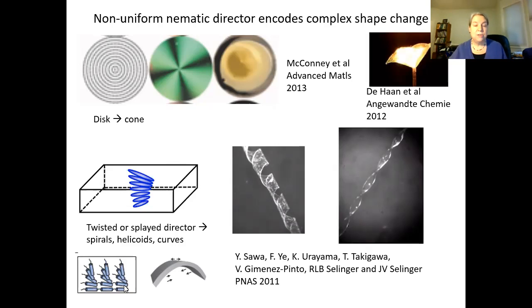And then the last thing we can do is we can put splay. So we can treat the surfaces that are used to form this liquid crystal, where on one surface, the liquid crystal wants to lie parallel to the surface in a kind of planar anchoring. On the other surface, it wants to lie perpendicular, what we call homeotropic anchoring. And that splay, when you heat it, the bottom side wants to shrink, and the top side is shrinking vertically, and that also gives rise to a bend. So these are a different sort of pattern elements that you could combine to make an arbitrary shape transformation in one of these materials. So they truly are programmable solids.